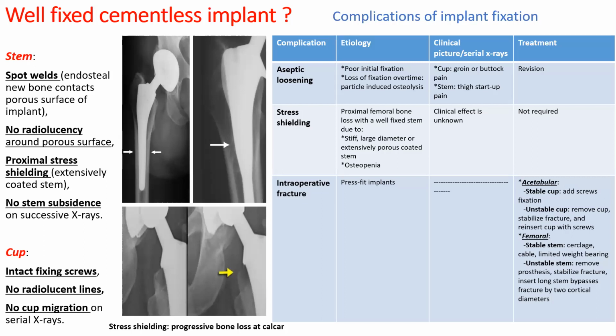However, in the postoperative X-ray, we can know if this cementless implant is fixed in a good way or in a bad way. We have some signs like the spot welds here, these points of endosteal new bone formation that can be seen in the X-rays in the follow-up periods. And there is no radiolucency around the implant, and the implant is fitting very well inside and is not subsiding inside the medullary canal. It's not going deep, sunken inside, or going out.